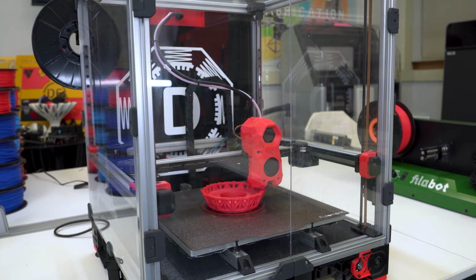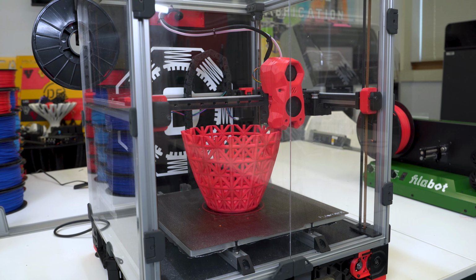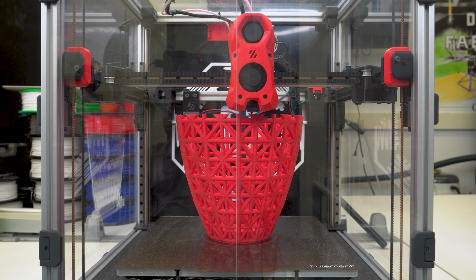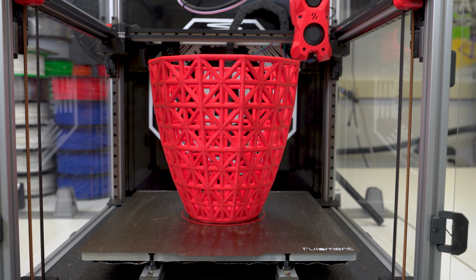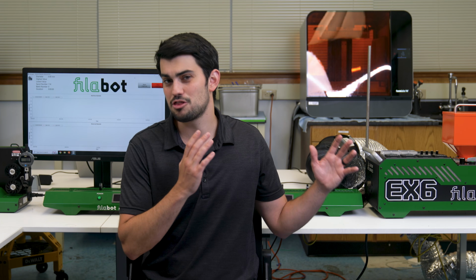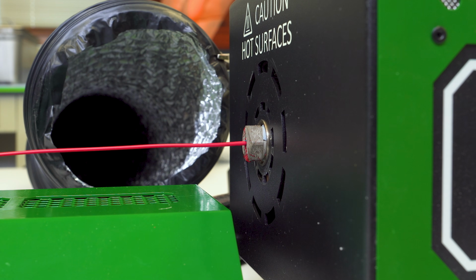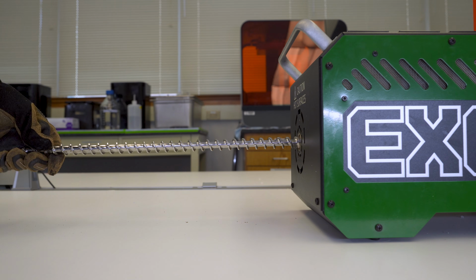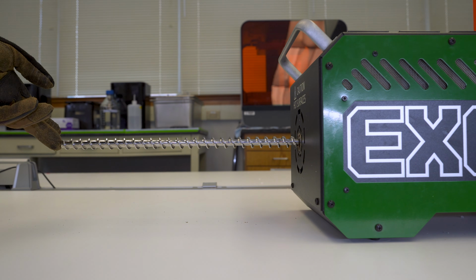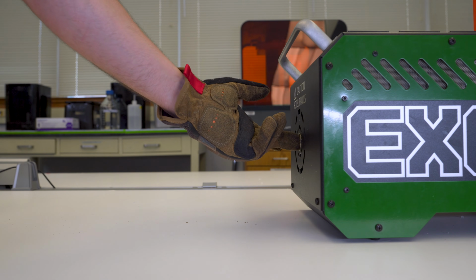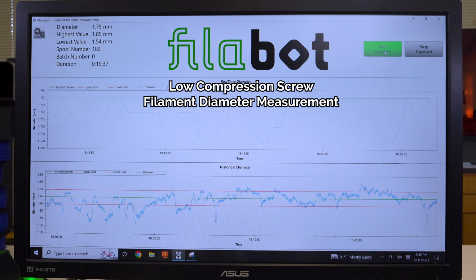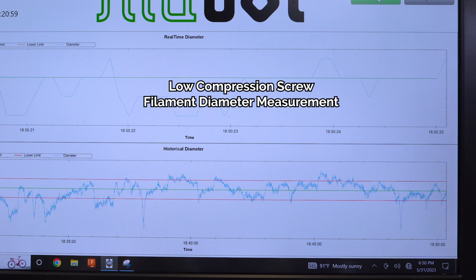I also use HIPS as a normal filament because it has great impact resistance, mechanical strength, and is as cheap as PLA for me to extrude. However, HIPS is thermally sensitive and can degrade if it experiences too high of temperatures or is heated above its melting point for a prolonged time. Given this, when I first tried to extrude HIPS, I opted for a low compression screw to minimize viscous heating. However, I was never able to get a consistent filament diameter, as you can see here.